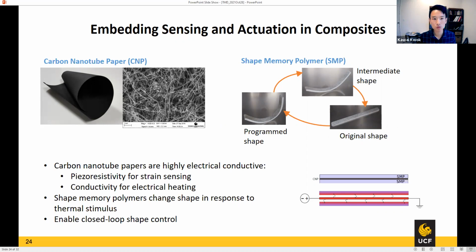So we make use of functional materials to achieve that purpose. We're using this carbon nanotube paper, which is very thin, made up of carbon nanotubes in a mesh, and very, very compliant. They're just like a veil of carbon nanotubes. This is a highly conductive material, so it's electrically conductive, and it's also heat conductive. We're looking also at a shape memory polymer that has this behavior where you can program the shape of the material by going through a mechanical cycle.